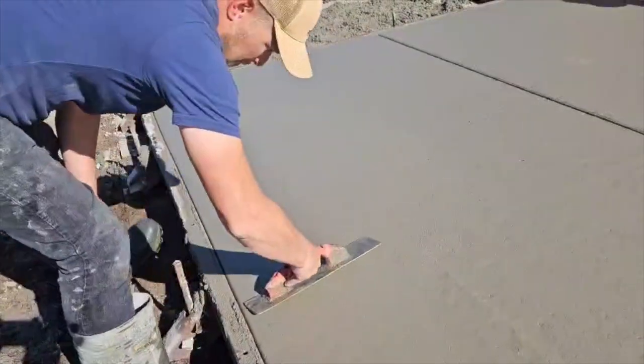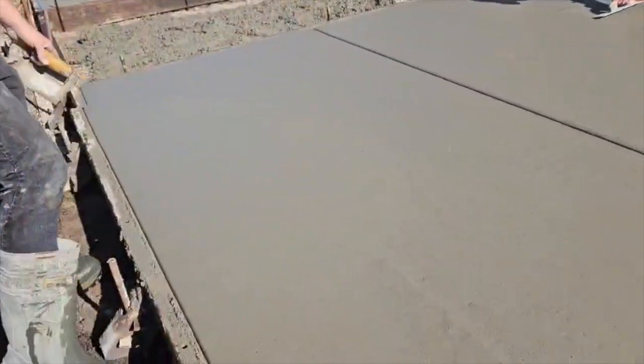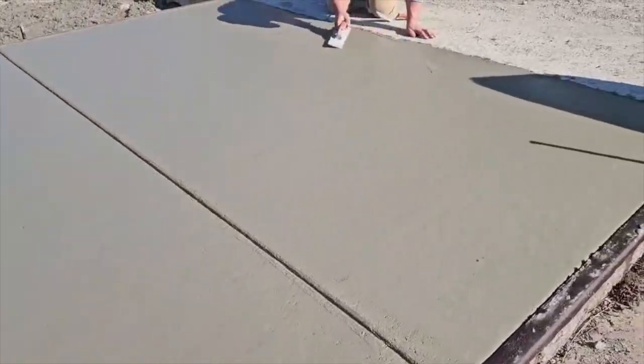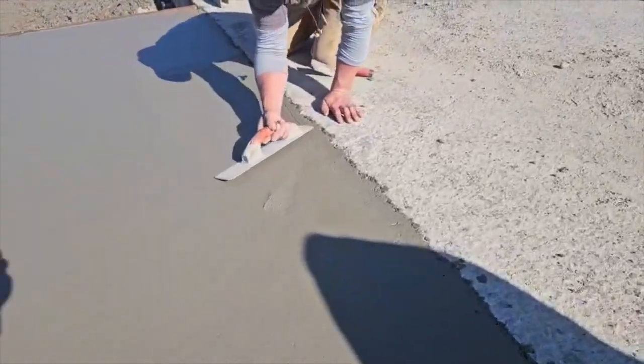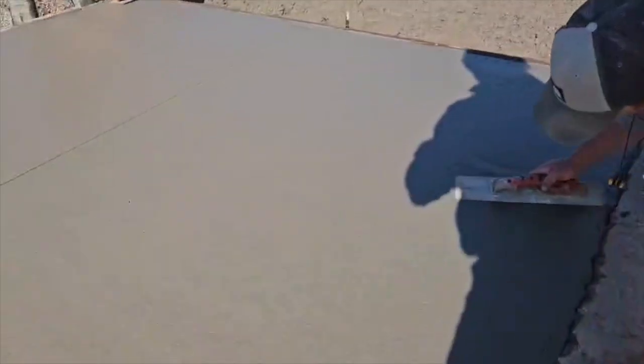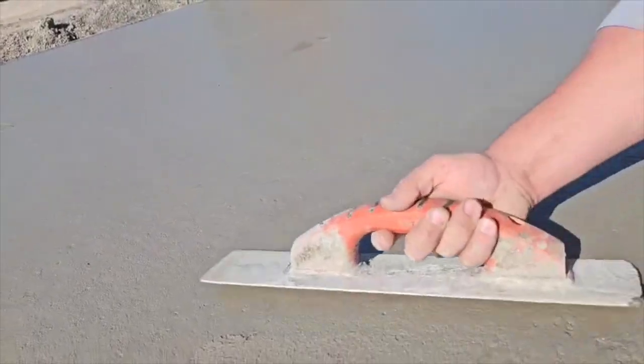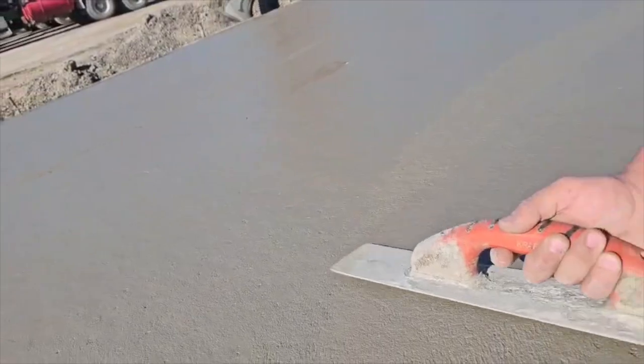So the first test, the slag at 20% cement replacement, we got about a 3.5 inch slump and about a 3.5 on the air. A little lower than I like and a little tighter than the guys liked. But it did work up well. It did provide enough cream, and it actually broomed very nicely.